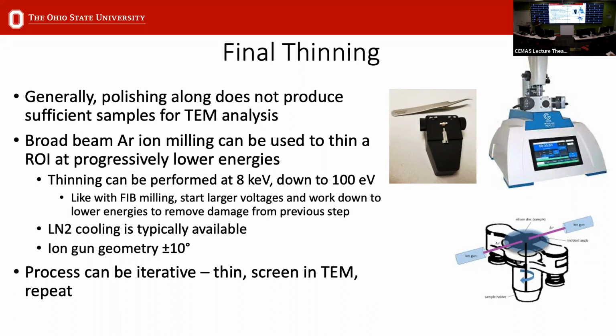In this case, you can also use liquid nitrogen cooling, and you can adjust your gun geometry. As you go to lower energies, generally you want to go to shallower angles so that you can clean your surface pretty well. And this, like all other steps in sample preparation, is iterative, where you would thin your sample, screen it, and then go back and forth.